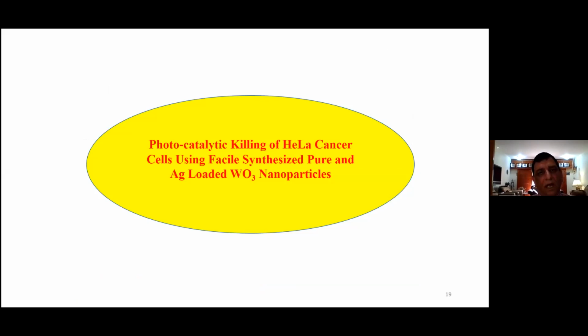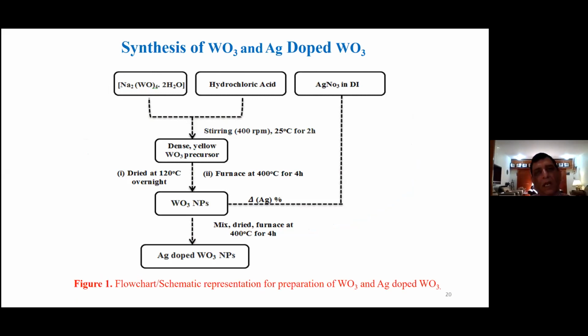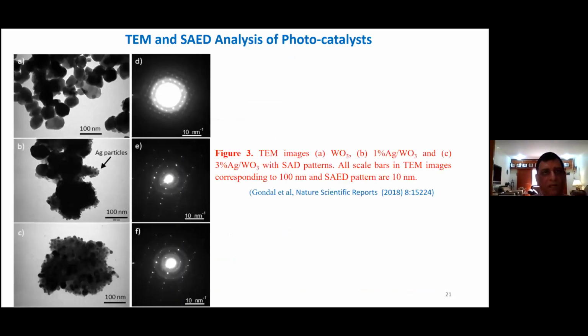Now I come to the studies which we have done. The first study we did was with silver-loaded WO3 nanoparticles. Here we use a wet chemistry method: sodium tungstate, hydrochloric acid, and silver nitrate. When we mix them through a precipitation process, we get silver-doped WO3 nanoparticles, which we characterize with normal and high resolution transmission electron microscopes. On the left-hand side, you can see that the particles are mostly spherical in shape, some of them. And we can also see the crystal lattice through the selected area electron diffraction technique.